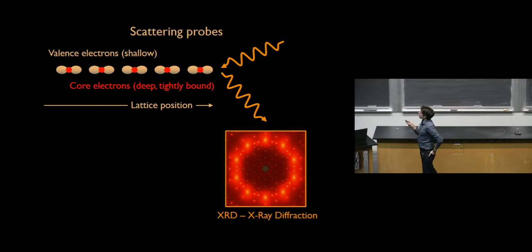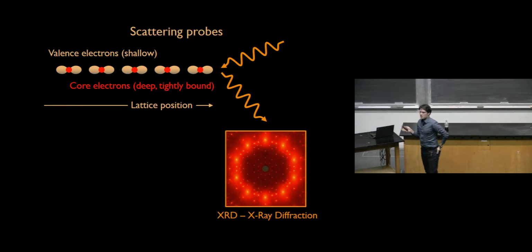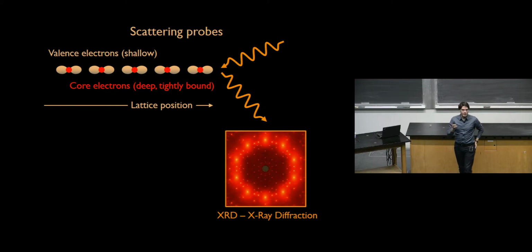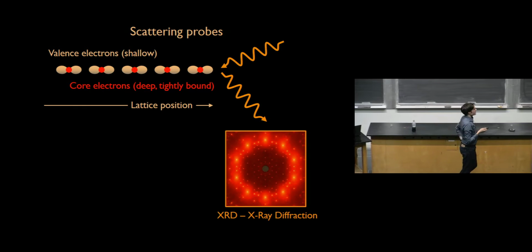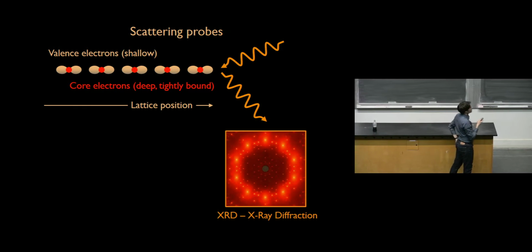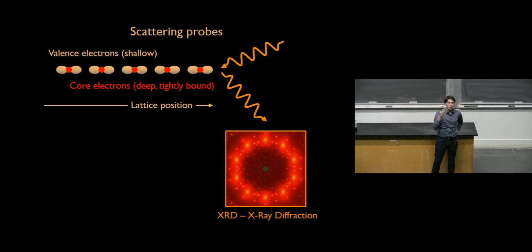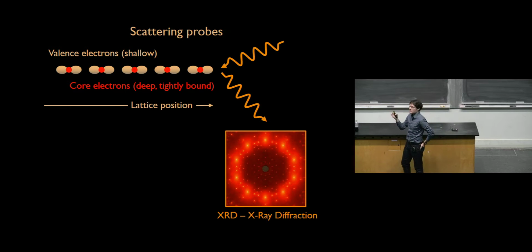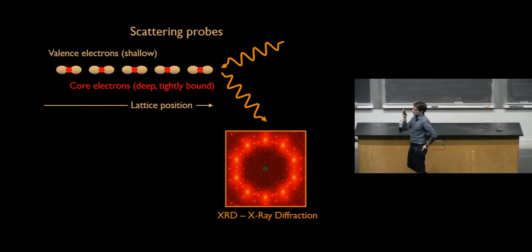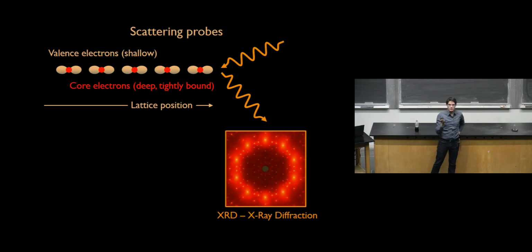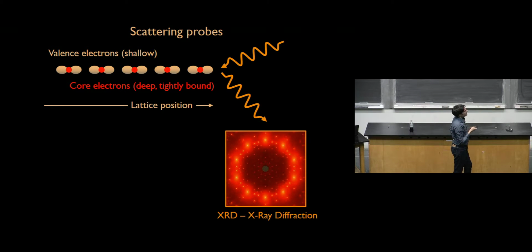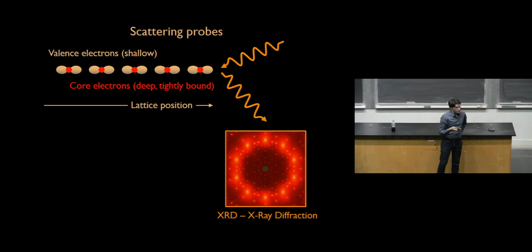So when we scatter off the electrons in a given system, in a given crystal, we're mostly scattering off the core electrons. And the contrast from the valence electrons, which are the ones that we're interested in, because they're the ones that can talk to each other and form these special types of electronic orders, is extremely small, to the point that it's non-detectable. So when you do crystallography, you measure the atomic lattice. And this is a problem, because now we're interested in measuring not the atomic degrees of freedom, or the atomic lattice. We're interested in measuring the electronic degrees of freedom.